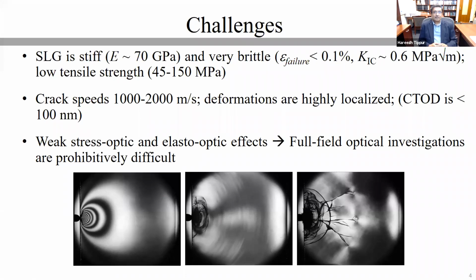At the low end, the tensile strength could be as low as 40-45 megapascals. And a crack in this material often travels very fast, typically in the range of 1,000 to 2,000 meters per second. So a mile per second crack speed is very common in glass, particularly under dynamic conditions. Deformations are highly localized. When you talk about a hairline crack, this is truly a hairline crack. Crack tip opening displacement is as small as 100 nanometers or less.